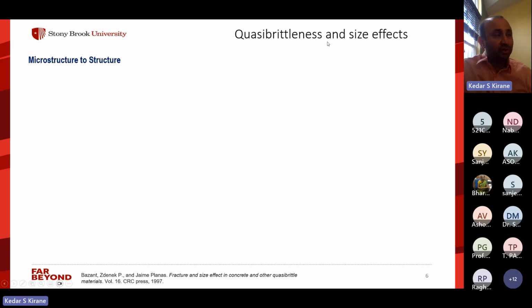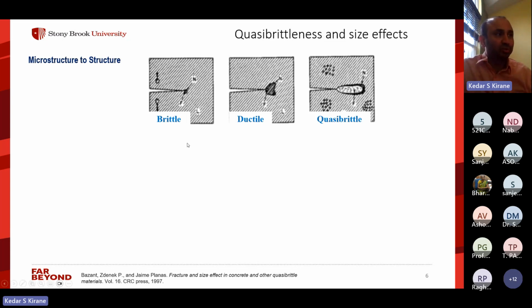So an important thing to understand is how the failure happens, and two, how it scales, like how it transitions when we go from smaller length scales to larger length scales. So one important point, or probably the most important point in understanding this scaling, is the so-called quasi-brittleness of composites. Now, failure can be of mainly two types. We all know that it can either be brittle or ductile. And when it is brittle, we know that if there is a sharp crack, then at the tip of the brittle crack, there is damage which is confined to almost a point. So the zone where damage is occurring is negligible. And for ductile materials like metals, there is a plastic zone which is not negligible in size. But there are quasi-brittle materials such as concrete, rocks, and also fiber-reinforced composites, where there is a damage zone which develops at the tip of a crack, and its size is not negligible in comparison to the size of the specimen itself.